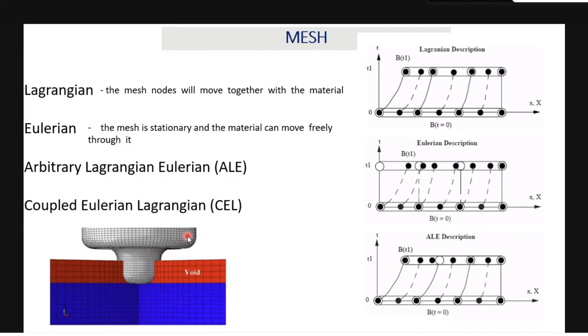Here the tool will be assigned as the Lagrangian and the workpiece is assigned as the Eulerian. So when we are using this, we can overcome such a problem which we faced in the ALE. Another problem is that if the friction stir welding process includes a lot of strains, a lot of material flow, you may have some problems, and you could not get the influence of flash.